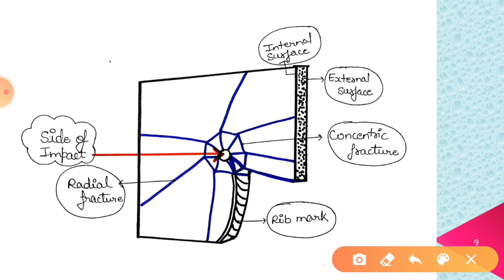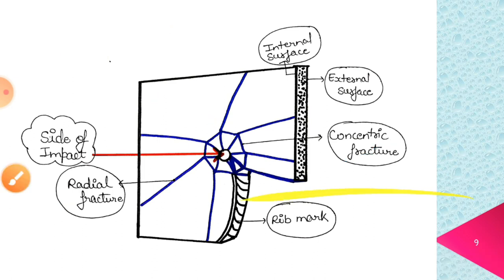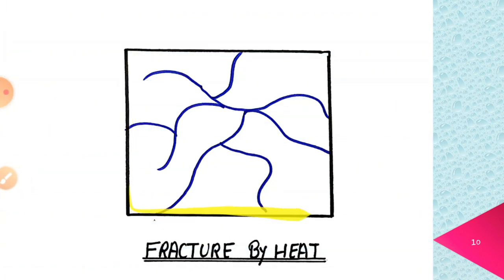The cone-like pattern is also very useful for determining the angle at which the projectile hit and also for determining the side on which the projectile hit the glass sheet. This is the overall summary of radial fracture, concentric fracture, and cone fracture. The fourth type of fracture is fracture due to heat. In this case, you can see several random and wavy lines present inside the surface, and these lines move outward from the point of contact of heat. This kind of fracture is generally found in arson cases and is completely different from radial and concentric fractures, because it does not follow any particular pattern.